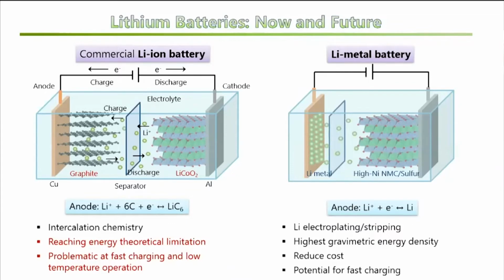So in this new type of mechanism, we directly electrochemically deposit the lithium ions that come from the cathode side to the anode side to form lithium metal. So this is the so-called lithium metal battery. By looking at the schematic, you can easily feel that by removing the graphite, our batteries can be much lighter, thinner, and easier for manufacturing.